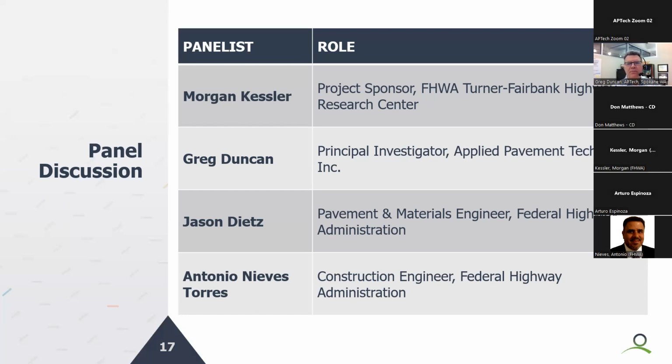So my understanding, Mike, I would welcome your opinion here, but in our discussions, you led us through where RAP would require little tweaks to the testing procedures and things like that, and it seemed like the most significant factor would be having to extract or use a furnace on the RAP to measure a true gradation of the material periodically. So that may be an addendum to the testing requirements for a typical pavement preservation project.